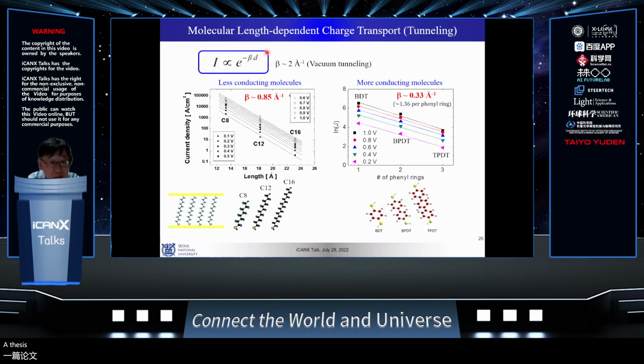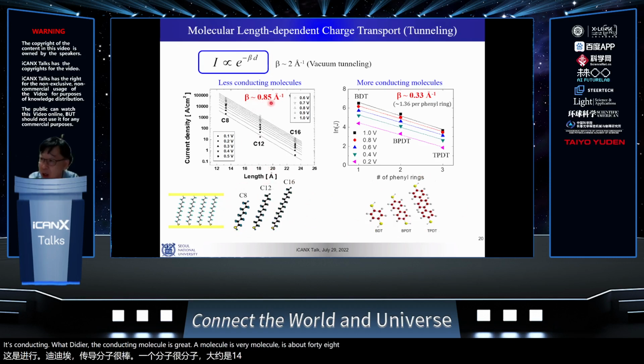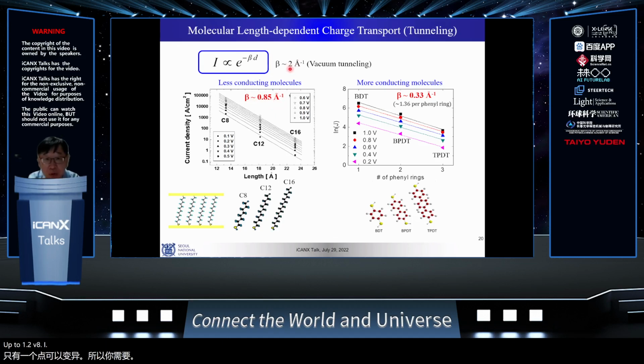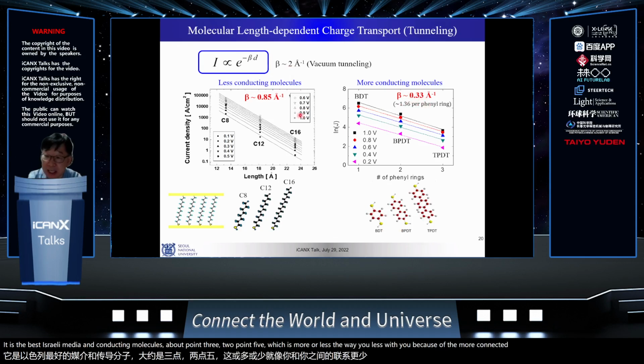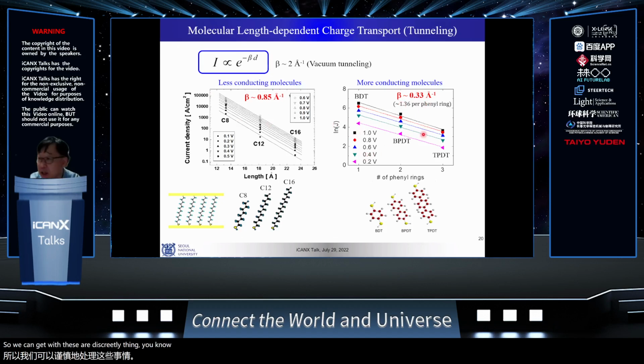This is the exponential dependence, and the exponential dependence beta value shows how quickly the electron current decays, and it depends on the material. So this is an insulating molecule, and this is a conducting molecule. The insulating molecule is about 0.8 up to 1.2 in these units. I told you the 2 is the vacuum, which is the best insulating medium, and the conducting molecule is about 0.3 to 0.5, which is a lesser value because it is more conducting. Okay, so we can get this tunneling physics mechanism.